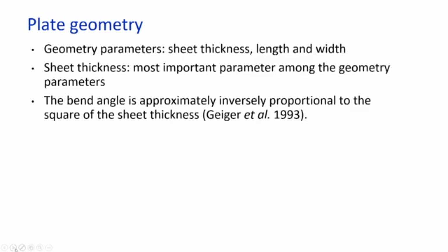It was noticed by Geiger that the bend angle is approximately inversely proportional to the square of the sheet thickness.